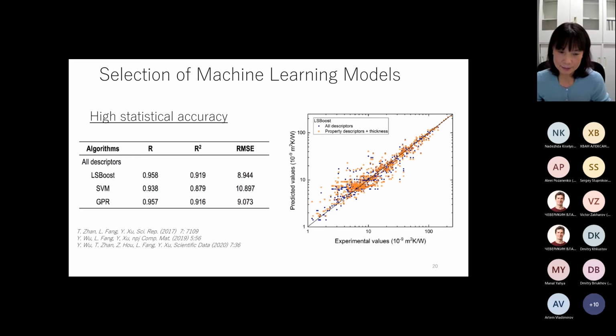From them, the first step is we compare the statistical accuracy of the models. And then we find 3 models with high statistical accuracy: LSBoost, support vector machine, and Gaussian process regression. If we just look at this R-squared value, all of these 3 methods can give a satisfactorily high value. And here is the comparison between the LSBoost prediction and the experimental value. We can see it's much more accurate than the physical model.